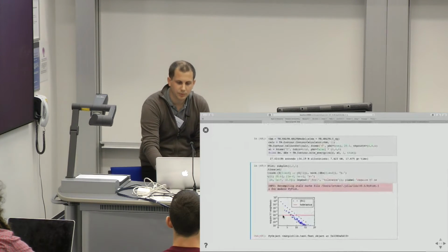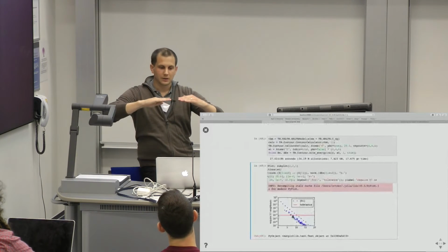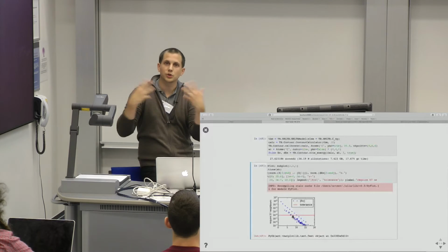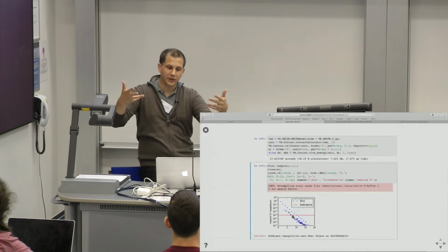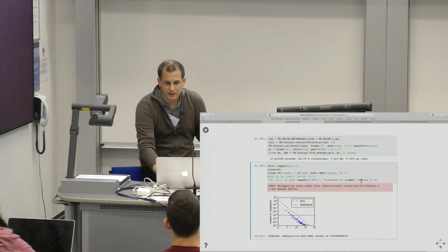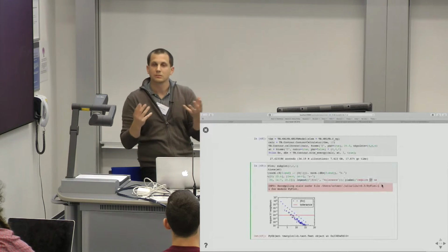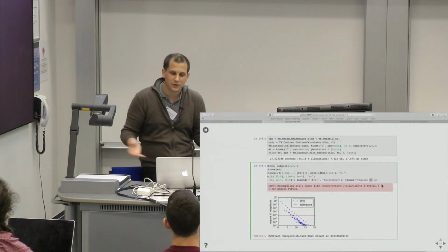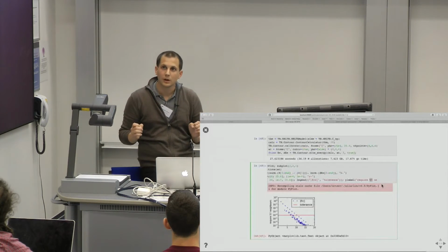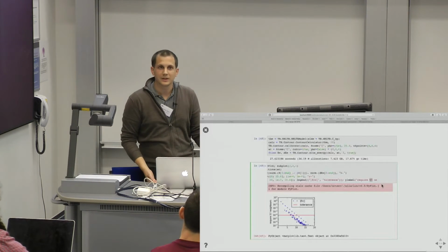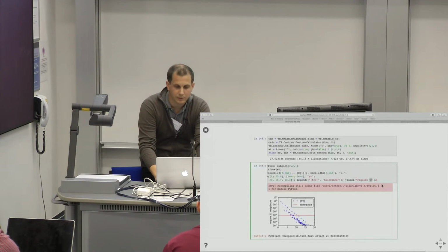So the red line here would be the tolerance, and that tells me everything that's below that are forces that are so small I don't care about. Everything above that, those are the forces I keep, and now I can count how many that is. That's 57 atoms I need to keep, and that is low enough that I am happy with that decomposition. So this is a quantitative result now on a real model that I can take away to use to continue with my simulations on something resembling a real model. Okay.